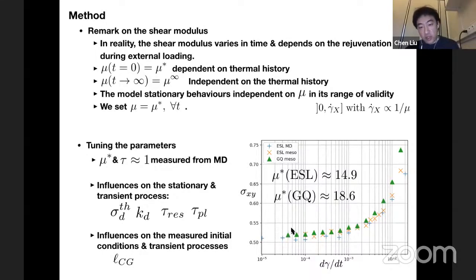The results for the meso model, namely the triangle and the orange cross, always use the same parameters, only with the mu different. You can see that in the small shear rate regime, the meso model agrees quite well with the molecular dynamics simulation results. Only at high shear rate do the two flow curves deviate from the molecular dynamics results. And the green triangle one deviates a bit earlier than the other because its shear modulus is larger.